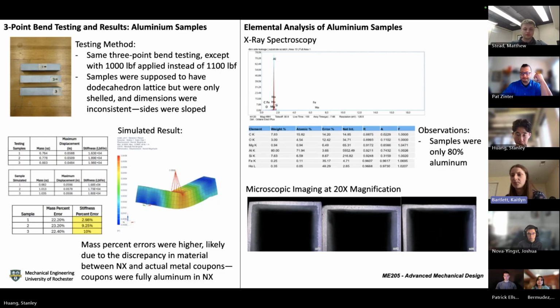From the microscopic imaging, we also saw that the shell thickness isn't exactly the same on every side. It's kind of sloped, as you can see in the leftmost image, and also the right one. You can really see how variable it is, and ideally it would not be like that. We were hoping it would be completely the same on all 4 sides. So when I was running these in NX, I took the average of the thickness, because I obviously couldn't model the sloped edges.